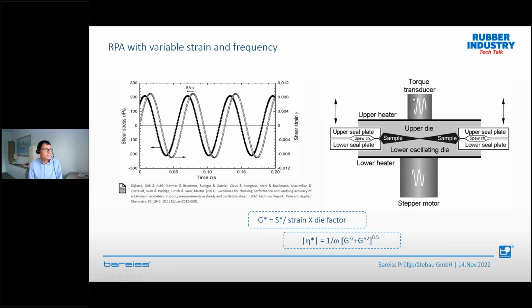So what you also see here, when we are talking about the modulus later and about viscosity, we don't measure a modulus or viscosity. What we measure is a torque. That's all. So what we have on the left side, on the sine curves, you see that we have a sine curve of the strain. That is what we apply with the motor. And we get an answer on the torque transducer on the top, the black line. That is what we get from our torque transducer.